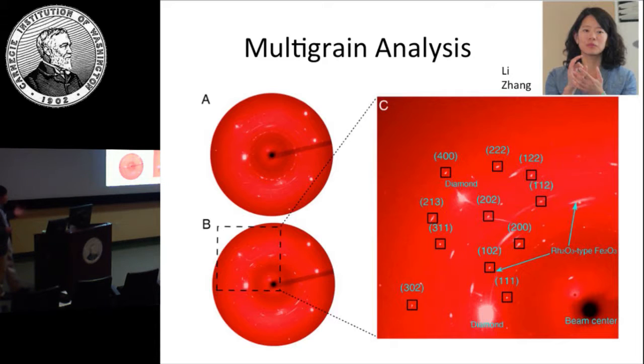I think that would be a new way for everyone to do high pressure, because the powder pattern has a disadvantage: you're never 100% sure of the structure. The single crystal is hard to maintain as one single crystal, and usually you end up with hundreds of crystals. But with this method you can analyze hundreds, even thousands of crystals, as long as they form individual grains. Then you can identify with some software each individual orientation matrix, and separate them, and find out how many independent crystals there are.